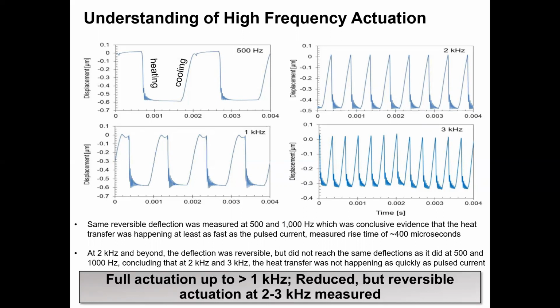In these curves, by pulsing a 1 volt signal, which was a square wave with 50% duty cycle, at 500 hertz and 1,000 hertz, I measured the same maximum deflection. In this case, it was 550 nanometers, and that's shown in the two figures on the left. These plots show displacement versus time, like was originally shown at the lower frequencies for the earlier characterizations, to confirm the two-way shape memory effects. The sharp dips and rises in this curve are indicative of the reversible shape change.